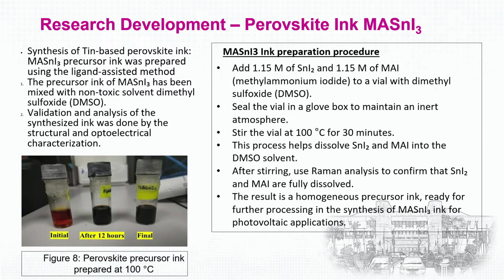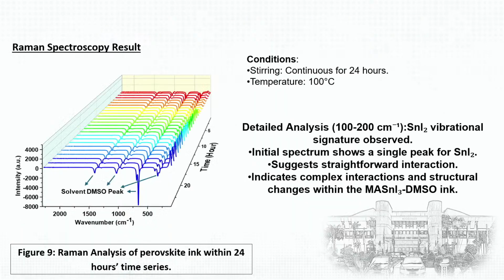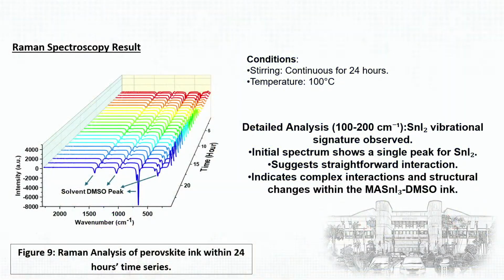So we use the ligand, then we do some property measurement using Raman, where the Raman shows the reaction time in order to mix these two materials. So this will be some solvent that has been applied in order to form this material.